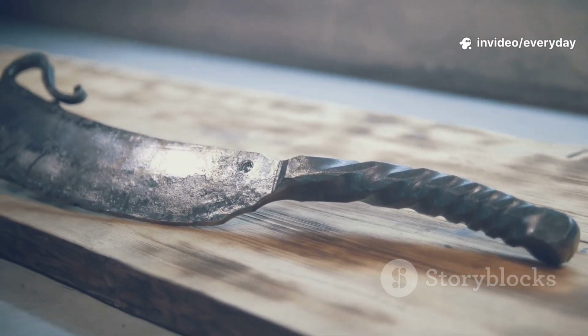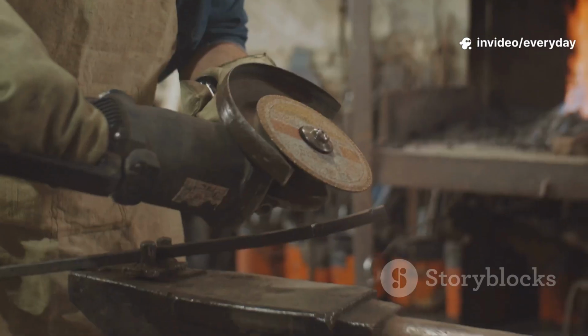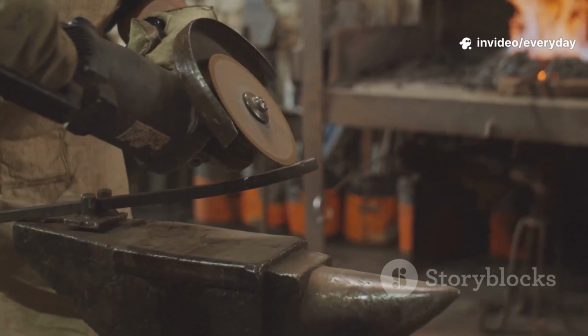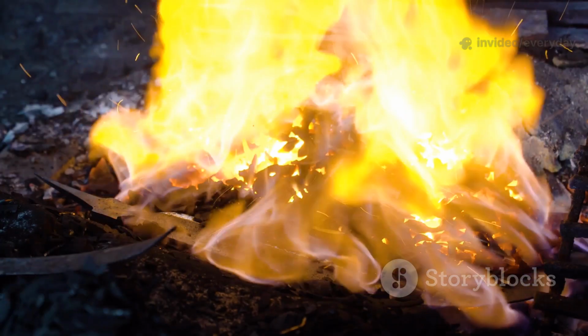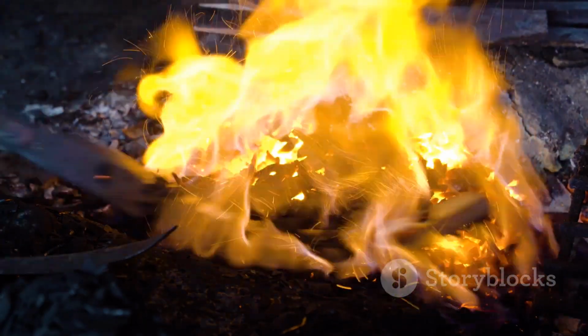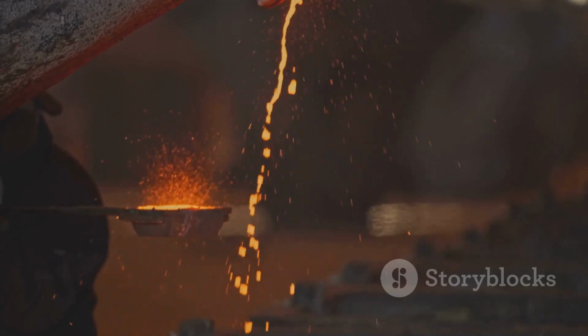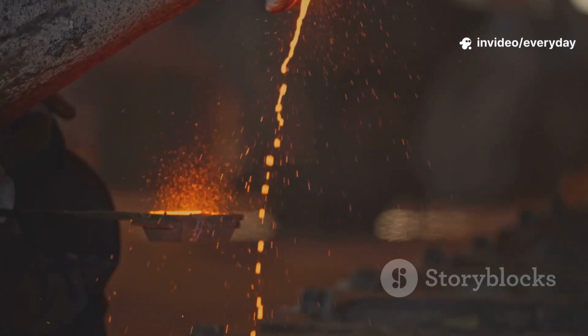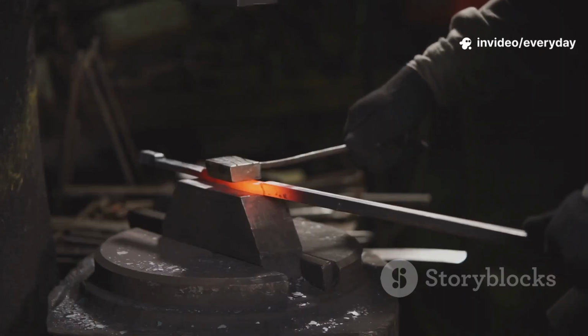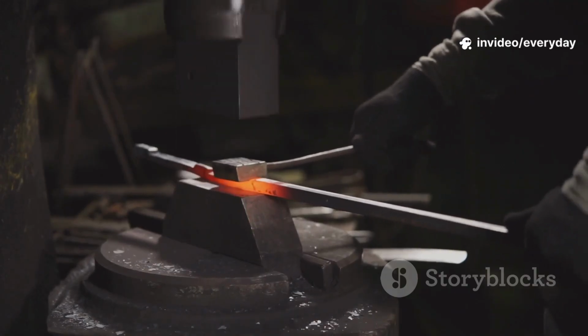Post-quench, it's glass hard and brittle. Handle with care. A fresh file should skate across a properly hardened edge. If warped, you have seconds to make gentle corrections before temper. Don't wait. Temper right away to relieve internal stress. The quench is dramatic, but timing and calm execution make it succeed. Right after quench, the blade is hardest and dangerously brittle.